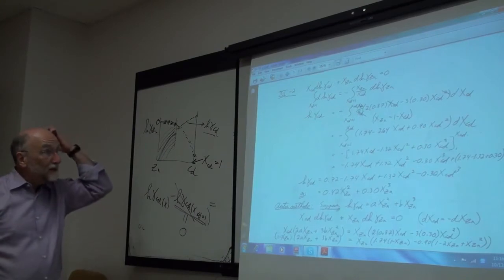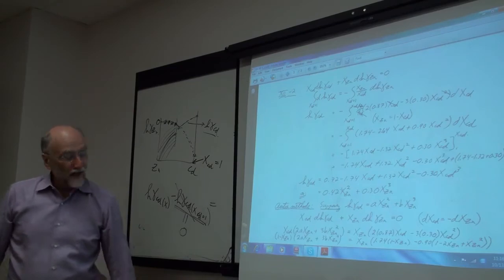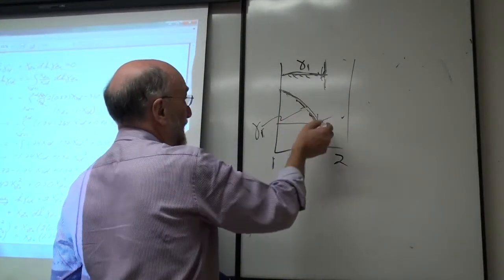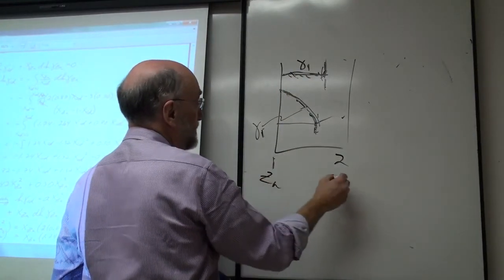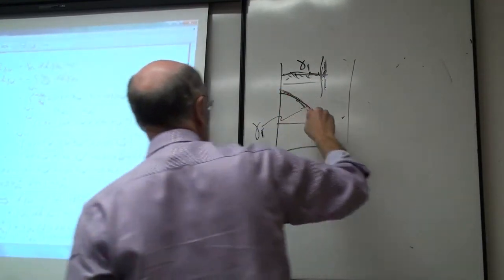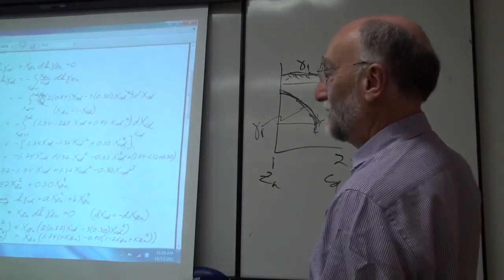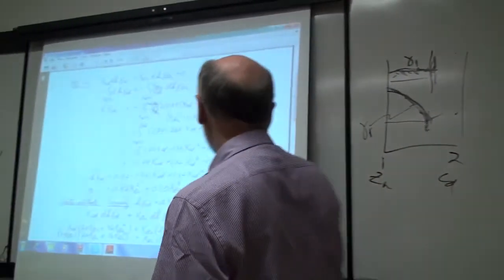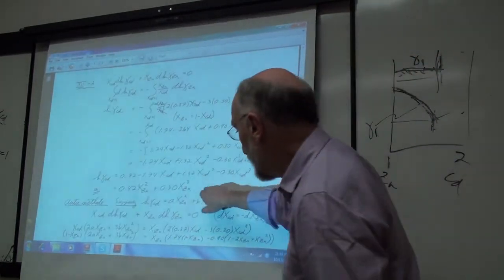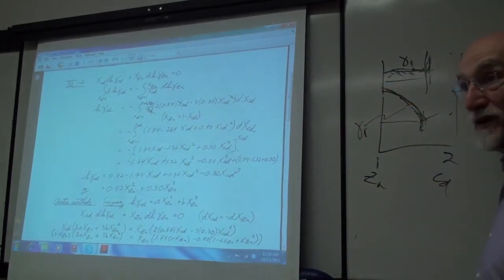But that log gamma cadmium isn't strictly correct because you don't have the endpoint. But you don't see that. Okay? You don't see the fact that you don't have the endpoint. You've only measured this is zinc and this is cadmium. You've only measured it up to here. And yet you're then saying that fine, that liquidus here has permitted me to get log gamma cadmium. So you fit your log gamma zinc expression from here, and then you get log gamma cadmium from this, but it's wrong. You've got a plus constant, and you don't know that constant because you don't have the log gamma zinc all the way to the end.